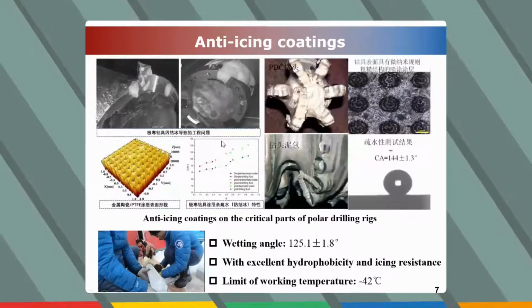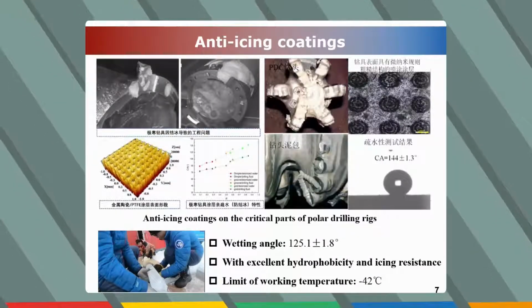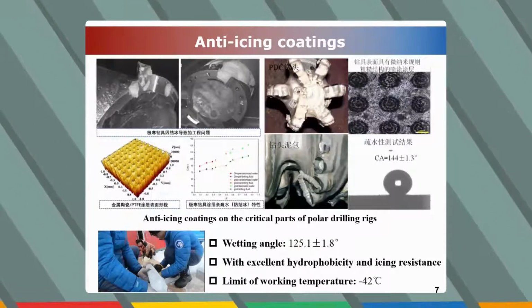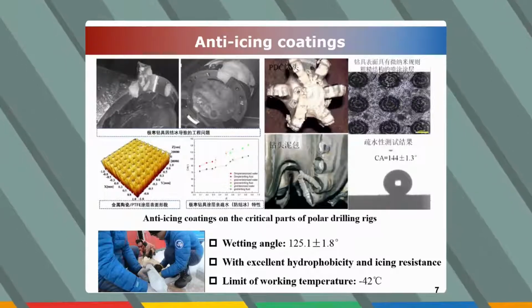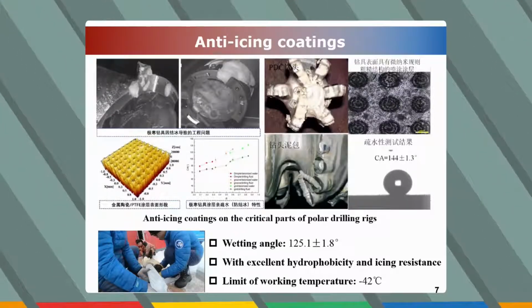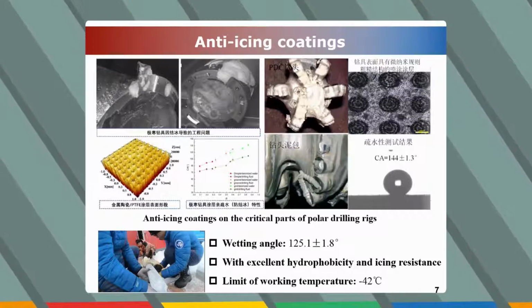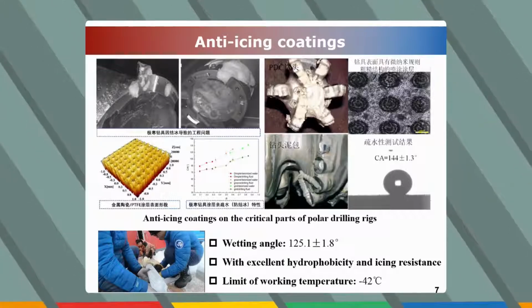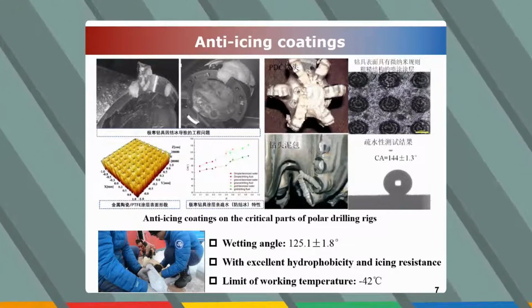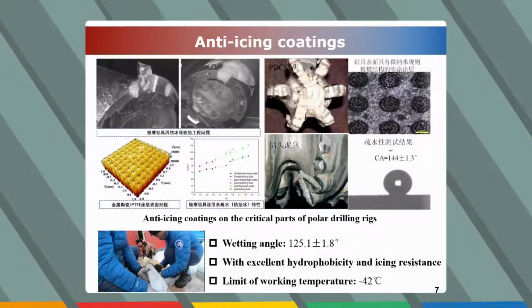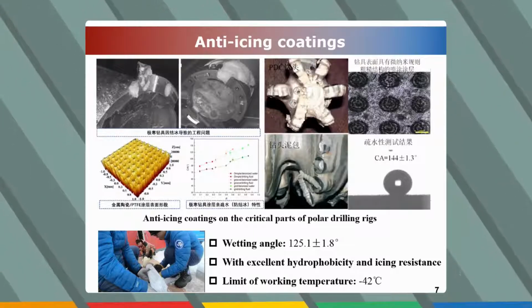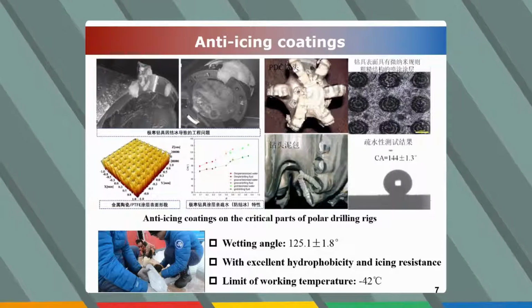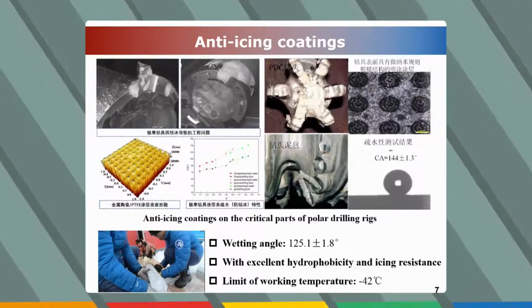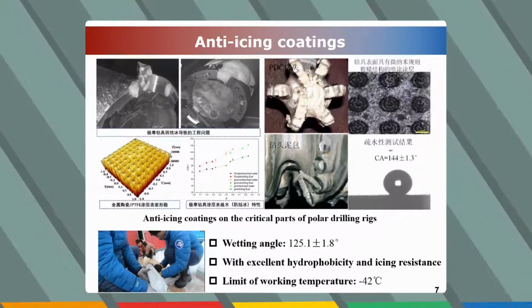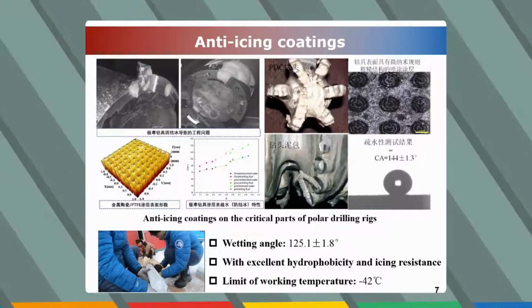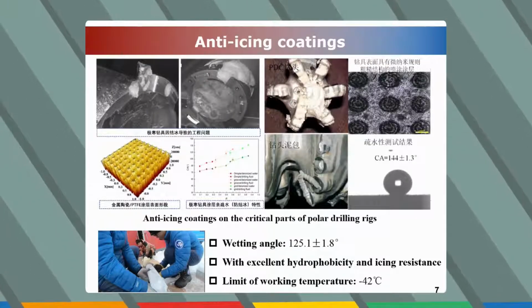Next one is about anti-icing coating. This type of coating on critical parts of polar drilling rigs results in a contact angle of 120 degrees, which gives excellent hydrophobicity and icing resistance, and makes the drilling rig able to work at the limit working temperature of -40 degrees.